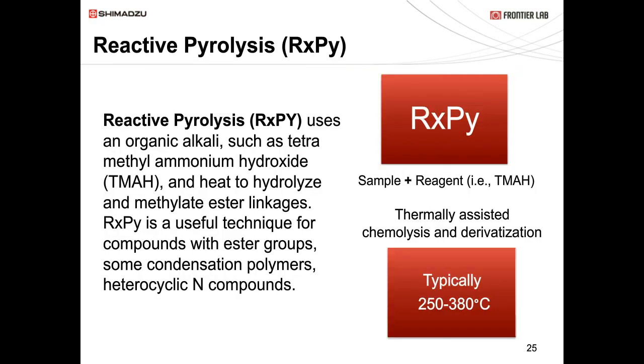For reactive pyrolysis: this is usually done for polymers that have carboxylate/ester functionality groups or condensate-type polymers. This is very similar to flash pyrolysis—it's an isothermal analysis, typically at 250–380°C. You use a reagent such as TMAH (tetramethylammonium hydroxide), add it to your sample, and that allows you to do more identification of the fragmentation for the polymer.